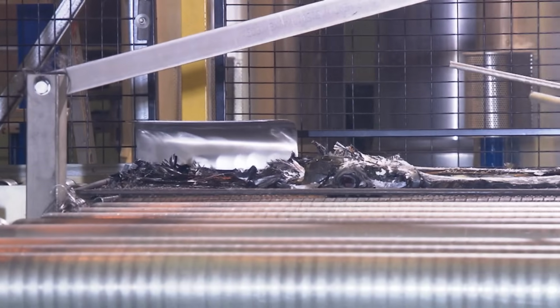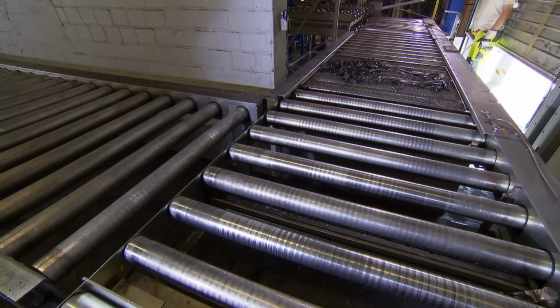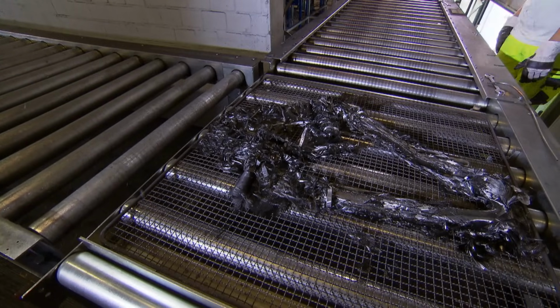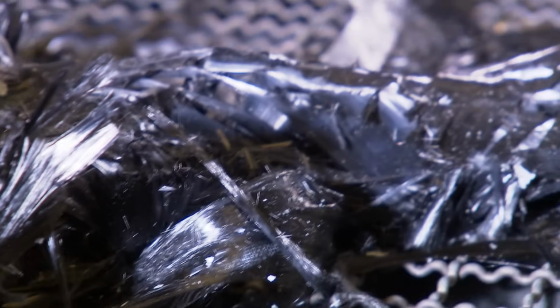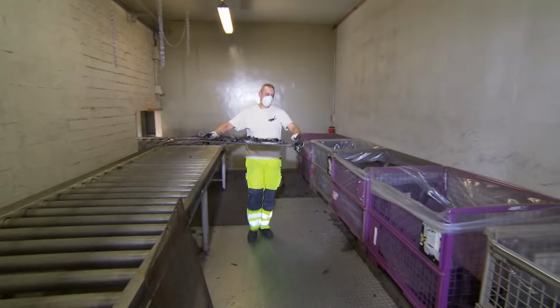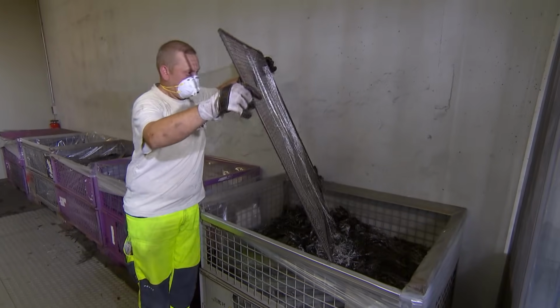After the pyrolysis, pure carbon fiber is all that remains of the bicycle frame. Metallic remnants are removed by magnets, and the clean process leaves the surface of the carbon fibers almost completely undamaged. Since there was no burning involved, no particles are attached to the fibers, and there's no change to the carbon structure, which is important for the stability of the material properties. The resin-free carbon fibers are now ready for the next step of the procedure.